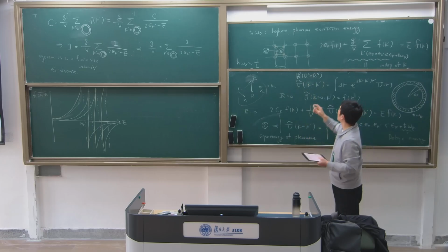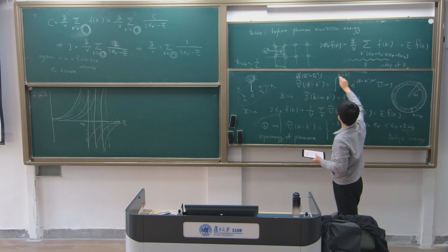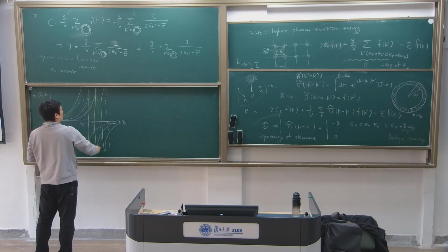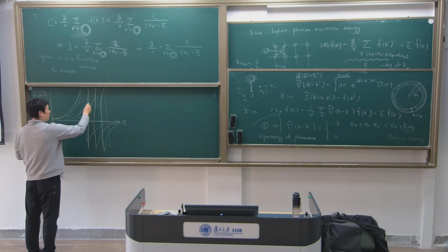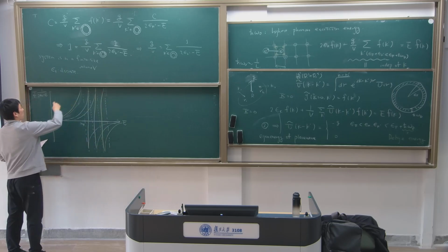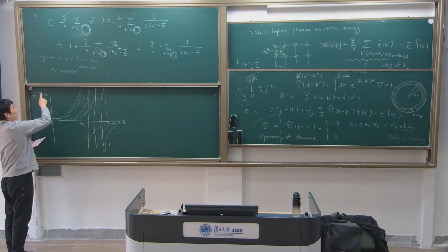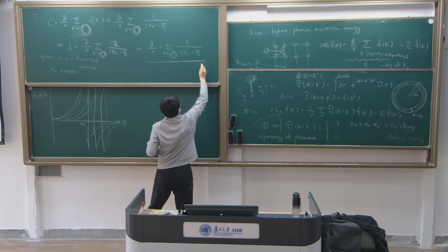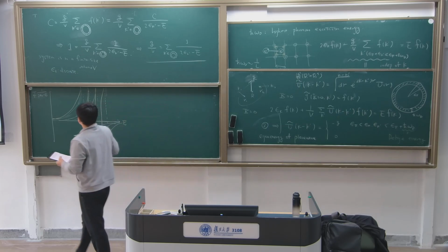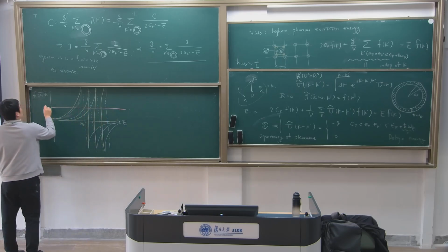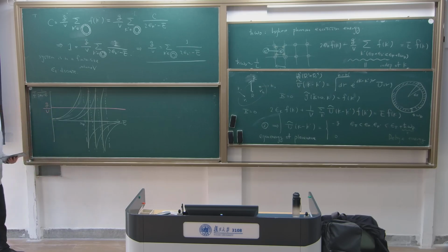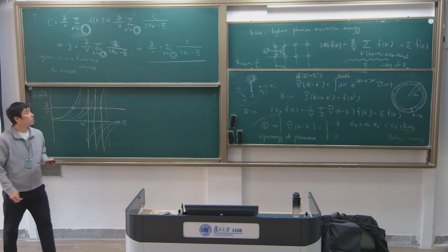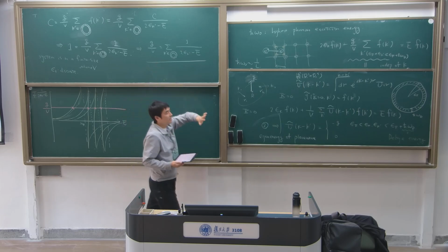And then just looking at only the K1 minus K2 part, and looking at each eigenfunction here above the Fermi energy, we have the first extended one, second extended one, third extended one, and you sum them up, all the one over 2 epsilon k minus E. Then it becomes yellow like this. And what we want is to find a solution of this equation. So I think what we need to do is look at the intersection between them. The intersection appears here and here and here and here. Those are solutions to this equation. So the solution to this equation means the solution to the Schrödinger equation.